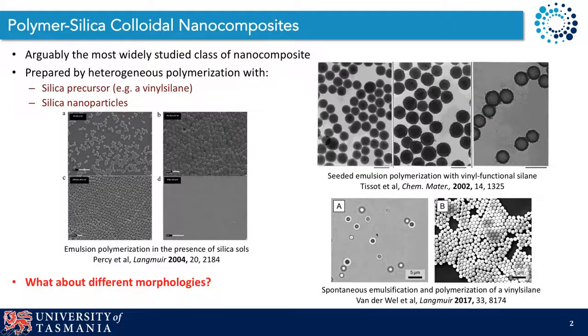So we've been interested in colloidal nanocomposites for a really long time, and polymer-silica composites are arguably the most widely studied class. There are lots of published methods for preparing such colloidal nanocomposites, primarily involving either the polymerization of a vinyl monomer with a silica precursor, such as a vinyl silane, or indeed the polymerization, such as an emulsion polymerization, in the presence of silica nanoparticles. But as you can see from the images on the screen, they all yield spherical morphologies as a resultant particle structure. So the question we asked was, how can we access different morphologies for such composites?